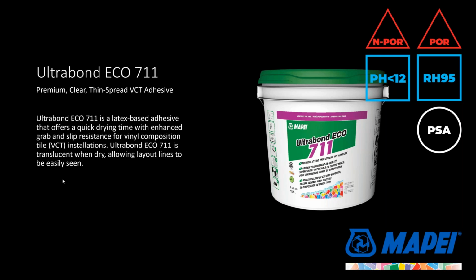This one is a little bit lower price point than some of our acrylic pressure sensitives and is the go-to product for installation of VCT, vinyl composition tile. Can only be installed in a pressure sensitive mode, which means all the water is going to come out. No touch to the adhesive can't transfer to the touch when you pull it out. It's got some relatively robust RH limits of 95%. I think the moisture vapor emission calcium chloride test is 8 pounds, whatever. Can be used on non-porous or porous substrates, again, but can be only used in a PSA mode as well, not wet laid at all.